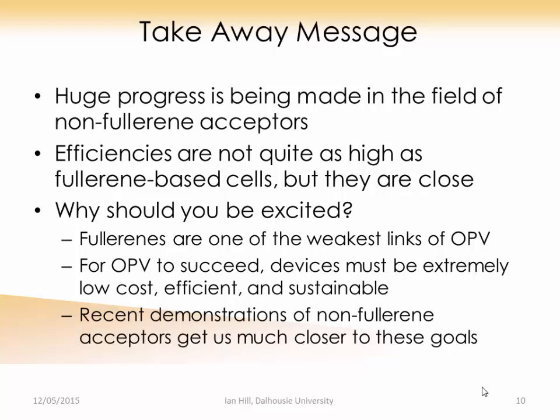And my guess is, a lot of these similar molecules, especially on the PDI side, have been used in things like N-channel organic thin film transistors for years. And the regular PDIs were not air stable, but people very quickly figured out that putting strong electron withdrawing groups on them to push the LUMO level down to make it more stable against oxidation, then suddenly you had air stable material. So I think it'll follow something similar to that.